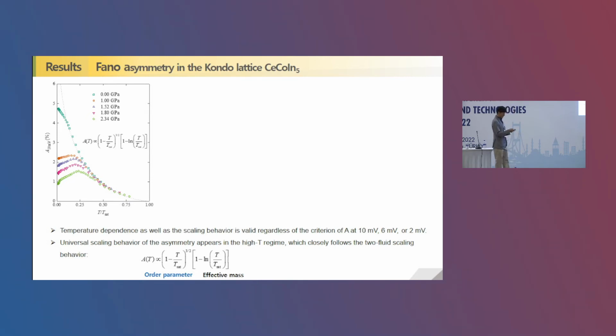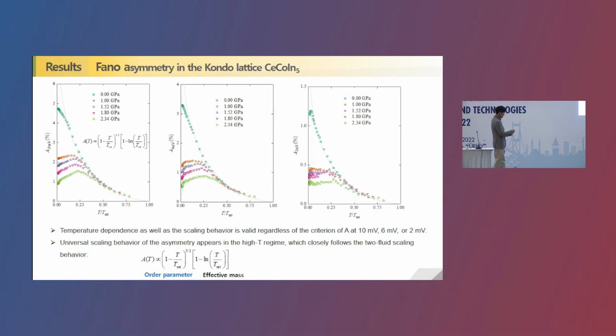In order to make sure that this is not just our arbitrariness in selecting the criterion, we also used 6 millivolt and 2 millivolt. Even though they differ quite a lot, they all show a scaling behavior and deviation at low temperature. So I think this is a pretty consistent result.